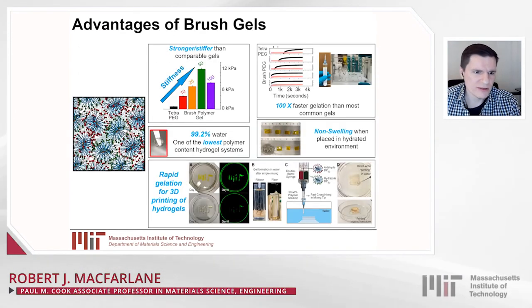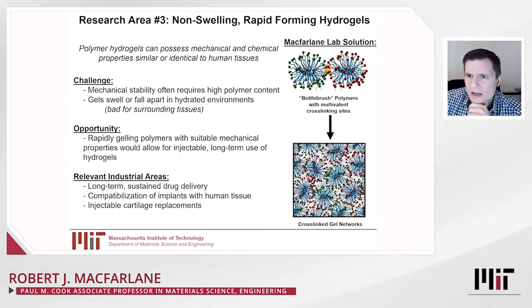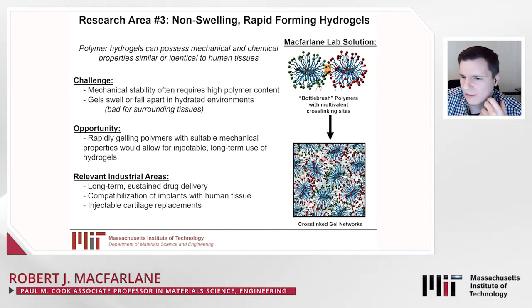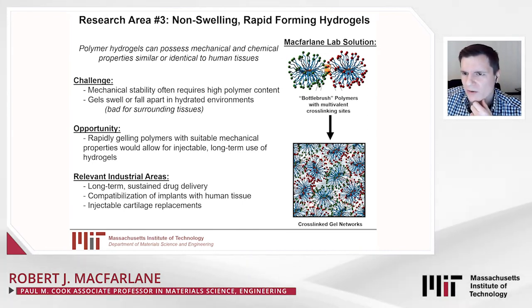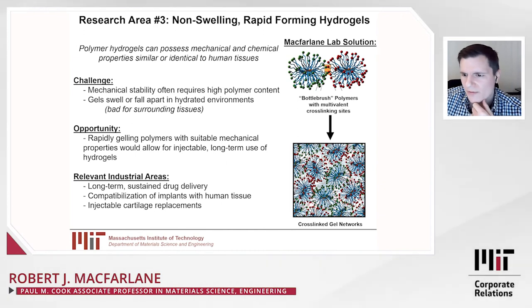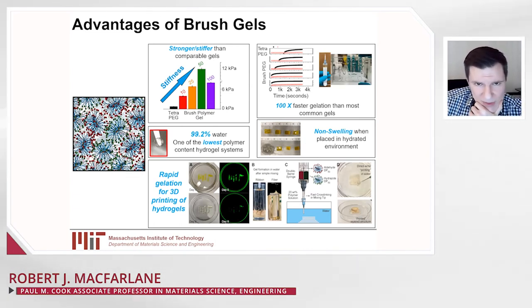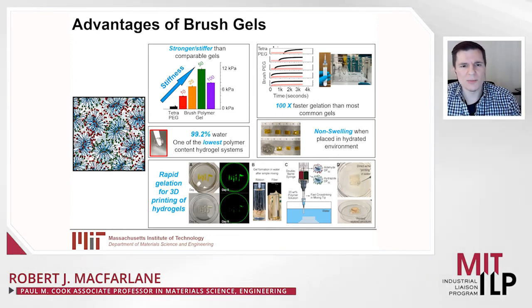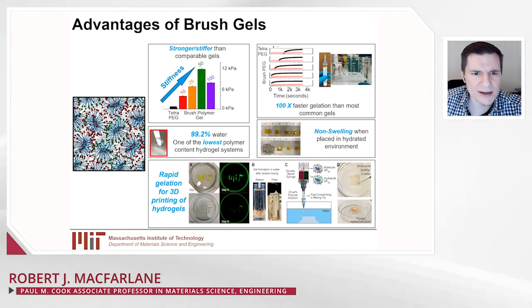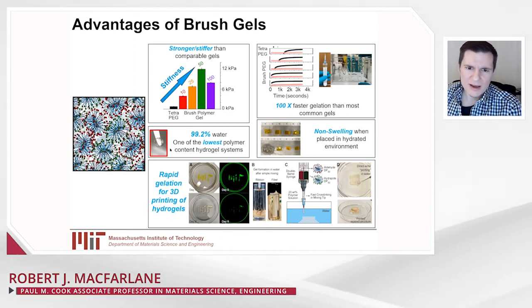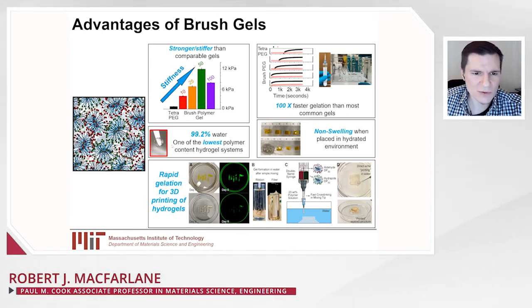The material we've developed is called a bottle brush polymer — a polymer shown here in orange where multiple short polymer chains come off a backbone, with cross-linking groups at the ends of those chains that form covalent bonds. Once two complementary polymer types are introduced to one another, they very rapidly form a networked gel architecture. The particular advantages are: first, they are stiffer and stronger than comparable gels made with standard polymers — using the same amount of PEG-based polymer, our brush polymers increase stiffness by an order of magnitude or more. We can also make gels with less than one percent polymer content that are still freestanding.